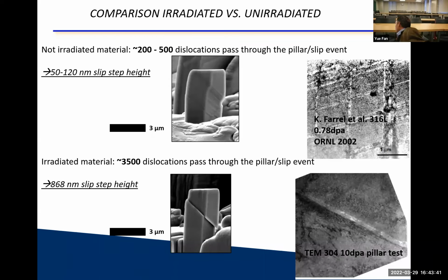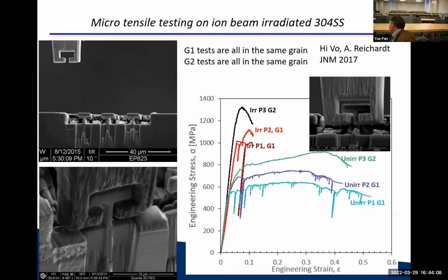This has been shown in reactor-irradiated materials that deform in these channels with no defects in them. And that's because these dislocations clean out the area and therefore leave these traces behind. However, any subsequent deformation will be in the same channel. And therefore, all the plasticity happens in this very narrow gap, which then leads to these load drops. You can do the same thing in tension.